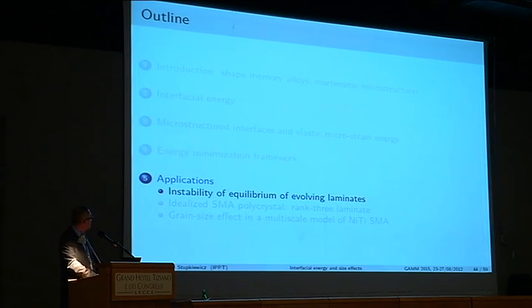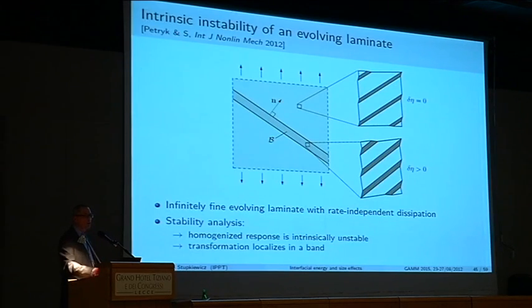Okay, so first, I show you some results of only qualitative analysis. I will not go into detail to take too much time, but we did stability analysis of evolving laminates, okay? So if you consider that this gray material is a laminate which evolves, so that the volume fraction of the phases changes during your process, and then you can check that actually this laminate is infinitely fine, so we have no characteristic length scale. So one can show that this kind of evolving laminate is essentially unstable. It's bad news, actually.